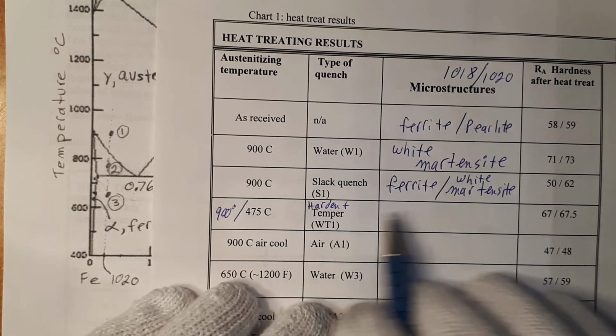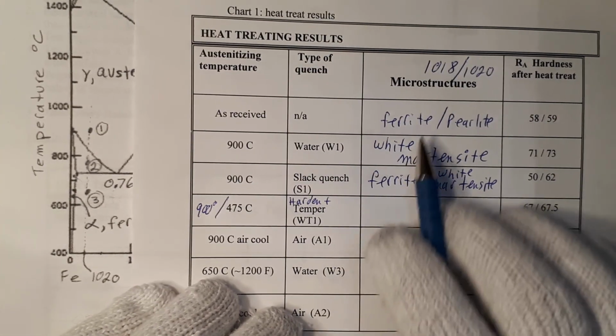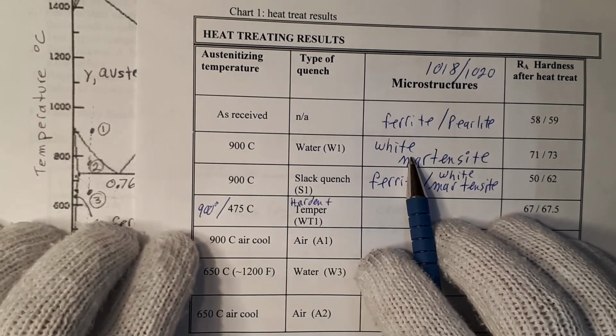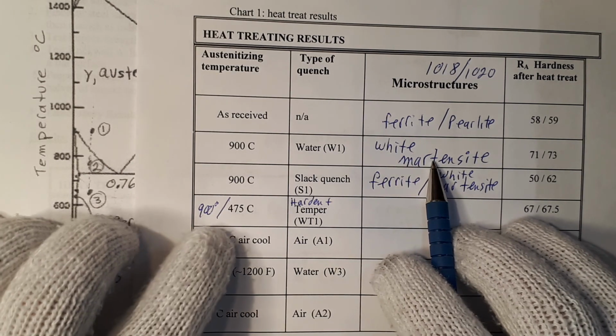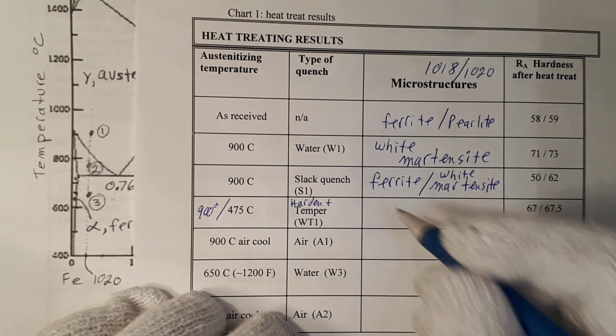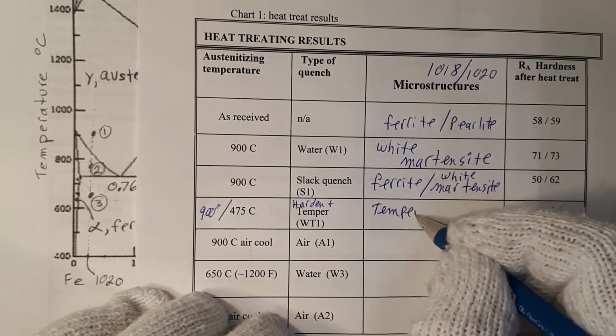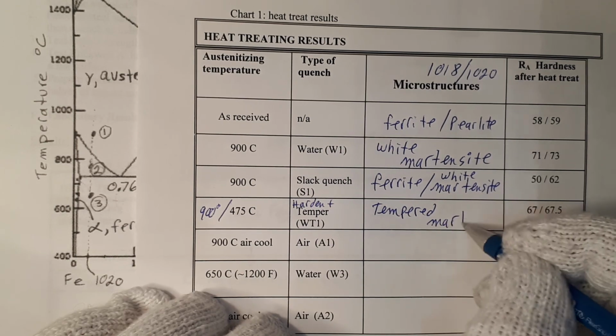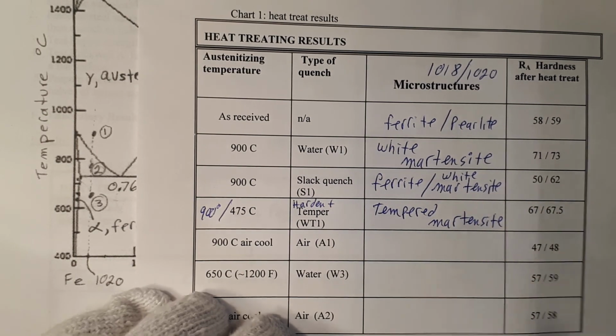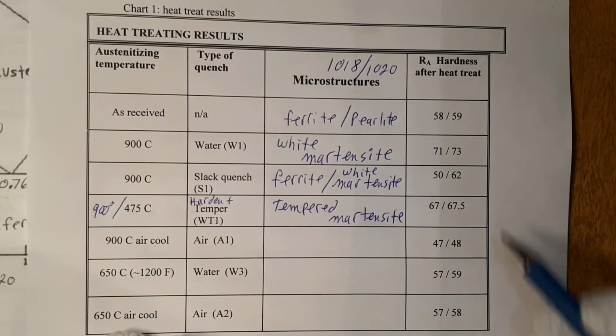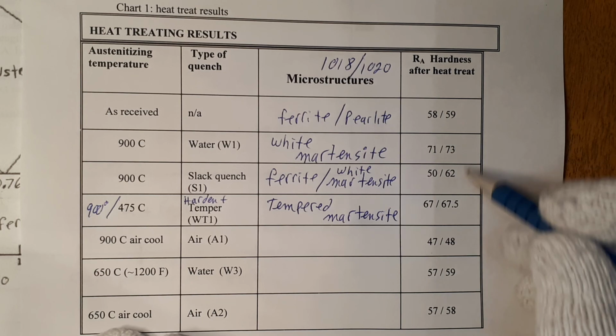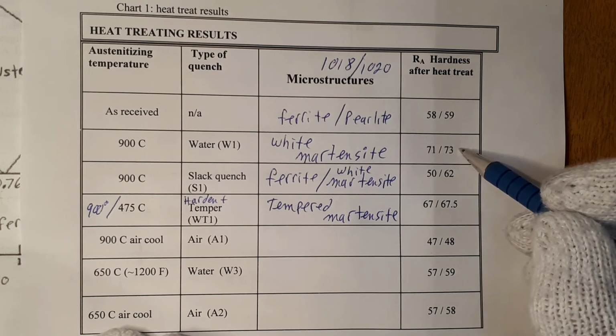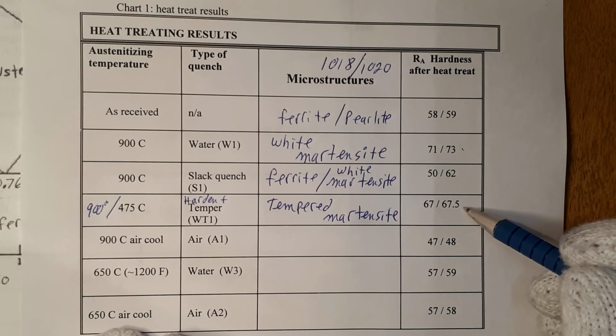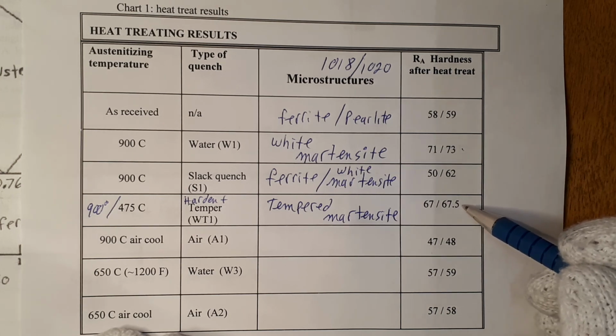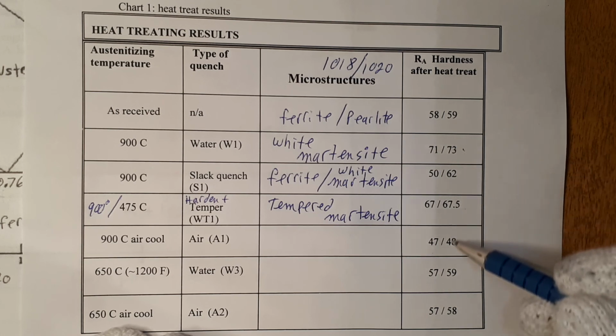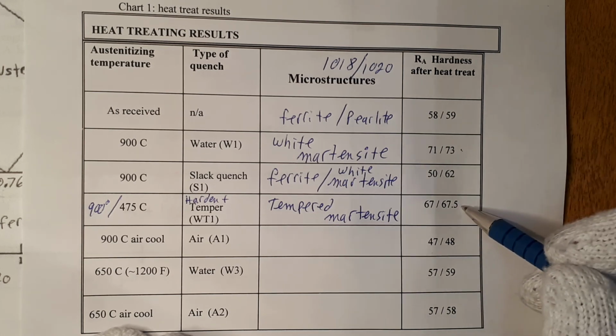materials for engineering purposes. What happens here is we'll form white martensite in the quench operation, and then this gets tempered back during the tempering at 475, and it has a special name called tempered martensite. It should have the second highest hardness on our column, the hardest one being the actual martensite itself. And then when we temper it back, we'll give back some toughness and lose some hardness in return. So it should also be the second hardest. And as you can see here in the hardness column, it is just that.